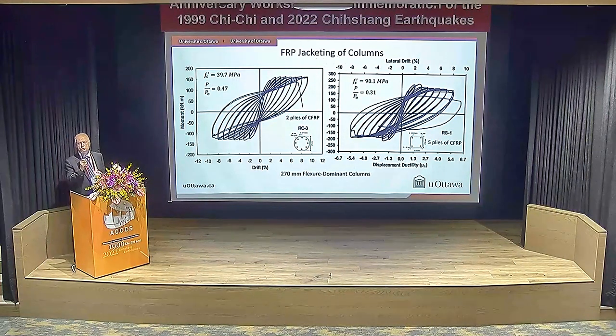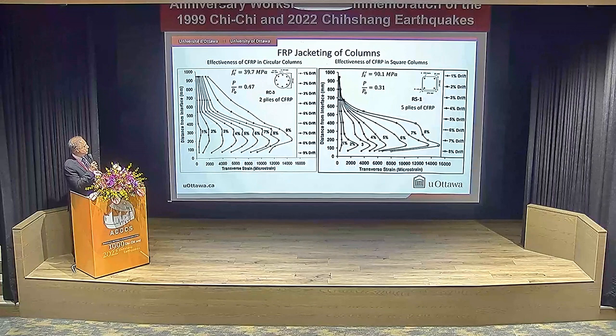However, when we used building columns under higher axial load, here we went up to 47% of P naught in one case, which was well above P balance, and on the right-hand side about P balance, 30%. And we tested circular and square columns. Square columns had either well-rounded corners or not rounded corners, because that was a parameter. Here you see we were able to actually rupture FRP. We were able to go up to 1.4% strain when axial load level was high.